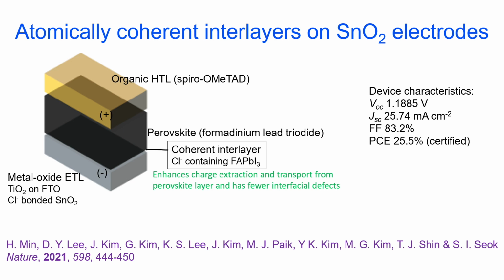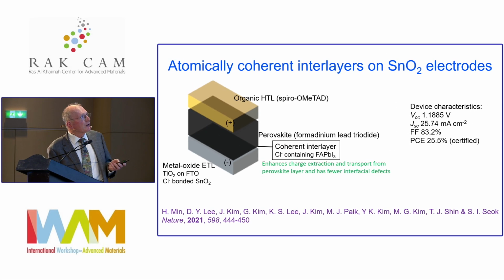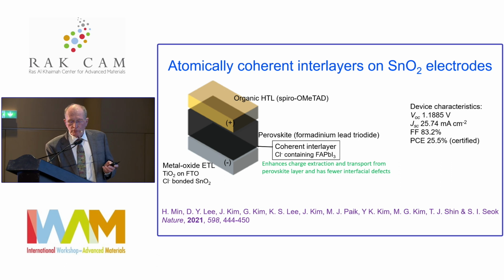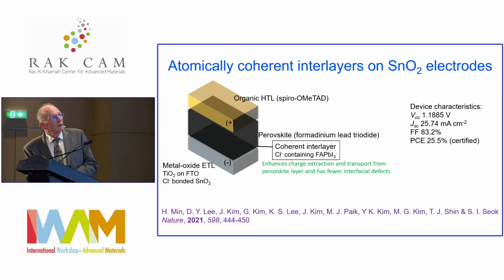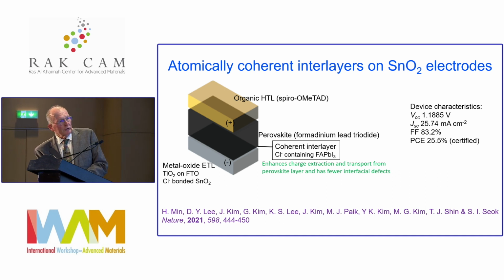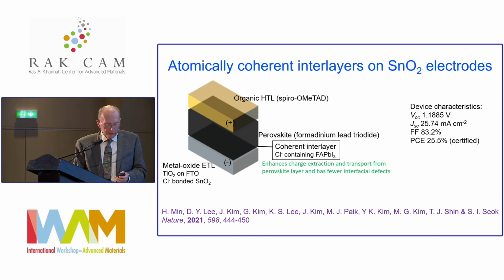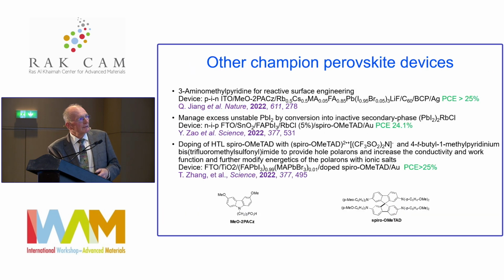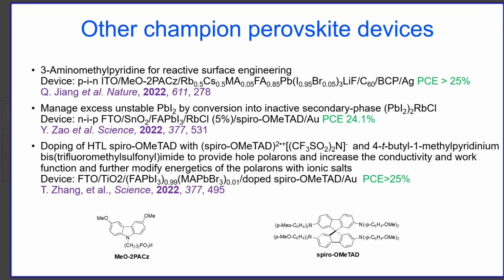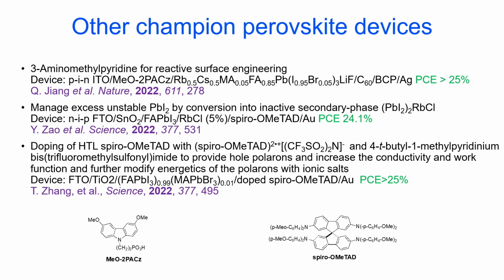And then the rest of the construction is conventional, if I can use that word: perovskite, formamidinium lead triiodide, and the organic hole transporting material is a molecule called spiro-OMeTAD. It's a spirocyclic molecule with amino groups on it. It's still to be beaten as the best material in this area for perovskites. I'll show its structure in a minute. And they're 25.5% certified. So it's starting to get quite seriously good numbers for a small device. And the spiro-OMeTAD is this structure here on the right.